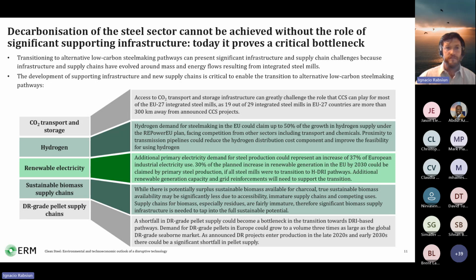For example, if you need access to hydrogen, well, the place where steel mills sit today is not necessarily the place where they can get access to that cheap hydrogen. The same for access to a CO2 transport and storage network. So we looked at different feedstocks and new supply chains that need to be developed. And we found that in the case of the CO2 transport and storage network, this is a great challenge for